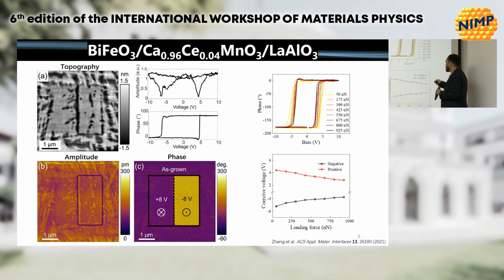Okay, and here are phase loops, or our local d33 measurements, or PFM phase loops, as a function of force. Again, maybe it's not so easy to tell, but the lighter color, yellow ones, are much wider than the higher force, dark color ones. So we've effectively shrunk, reduced the coercive field on both sides. So it's a symmetric effect in this case. And that's shown here. You can see our coercive voltage plotted as a function of loading force. And you can see that it's shrinking on both sides. The applied force is causing a reduction in the switching voltage in both cases. And from our understanding of the flexoelectric effect, we would expect that not to be symmetric. So we think that while flexoelectricity is involved, there's another thing going on in this work.